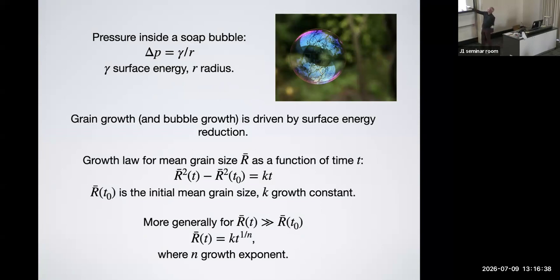The pressure inside a soap bubble can be represented by that simple equation, right? So the pressure differential between inside and outside depends on the surface energy and then the radius of the soap bubble. And you can lower surface energy by increasing the radius. And that is the principle that drives, if you look at foam, you see that the bubbles in a foam increase in size as they mature. And that's very much the same driving mechanism for grain growth. So it's a reduction of the free energy of the system, expressed here by surface energy. So the less surface in the system, the lower the energy.